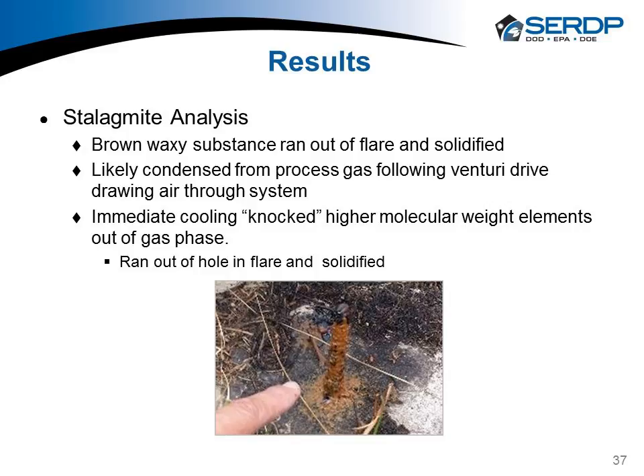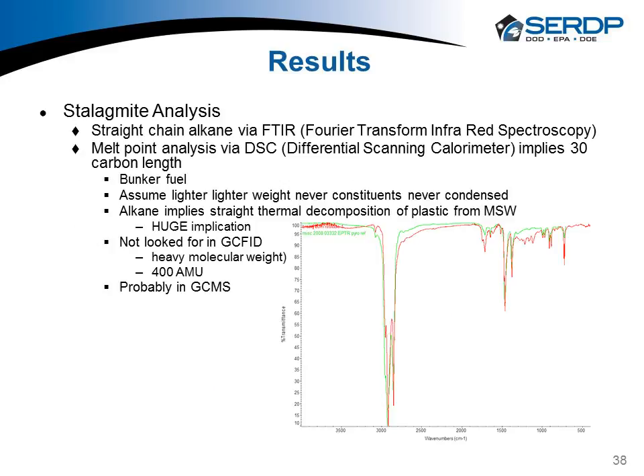And we happen to have a hole in the flare that this stuff was pouring out of and then condensed into that little stalagmite. We looked at it with FTIR, and we see that it's pretty much an alkane material, straight chain hydrocarbon, fully saturated with hydrogen. Based on a differential scanning calorimeter, it's about 30 carbons long, which is essentially bunker fuel, the stuff we use on boats. And probably there were lighter weight alkanes, but they didn't condense and form a stalagmite, or if they did, they probably would have evaporated away.